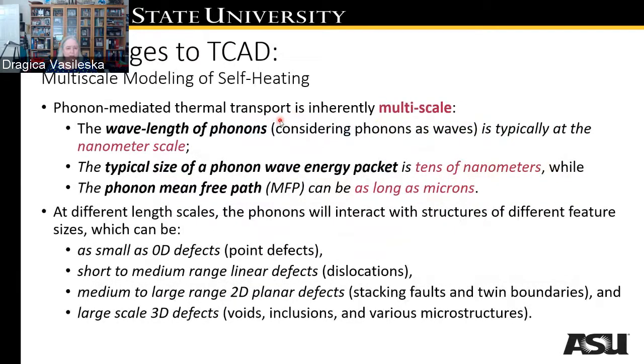Talking about self-heating, that is the second problem that I extracted because it is a big challenge to TCAD and multi-scale modeling. By nature, self-heating is a multi-scale process because the wavelength of phonons is typically at the nanometer scale. The typical size of a phonon wave energy packet is tens of nanometers, whilst the phonon mean free path can be as long as microns. For example, in silicon at room temperature, the phonon mean free path is on the order of 300 nanometers. Now, what complicates things is that at different length scales, the phonons will interact with structures of different feature sizes, which can be as small as zero-dimensional defects.